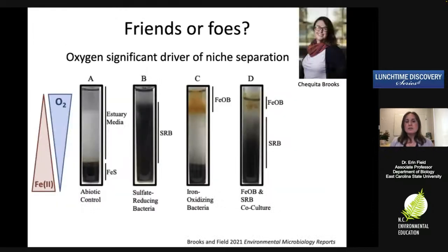And it turns out we can use what we call gradient tubes. And that's what you're seeing in this picture here. So we have oxygen in the headspace. And oxygen will diffuse through this agar or agarose material. Think of it as almost like a jello-like material. Then we have sulfide, which will go up and interact here, and it'll basically get rid of all of the oxygen in this low section.